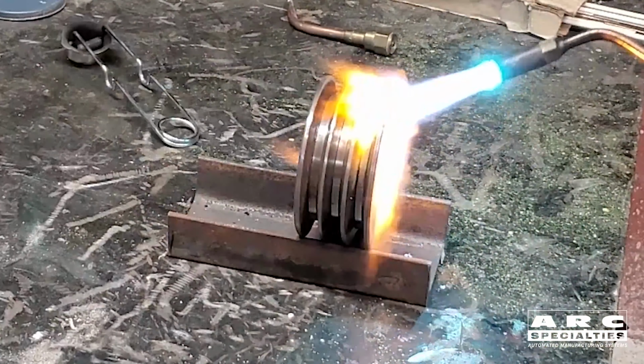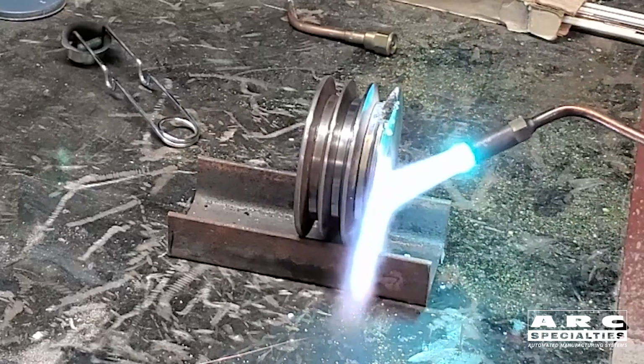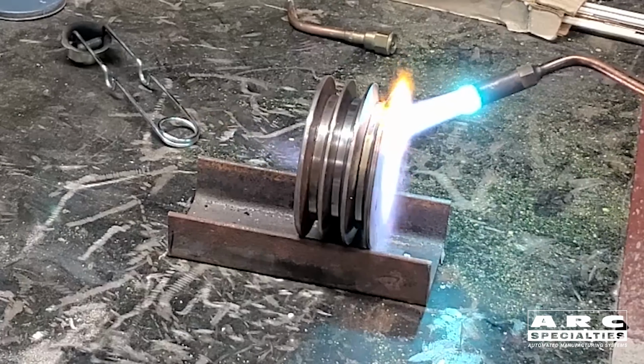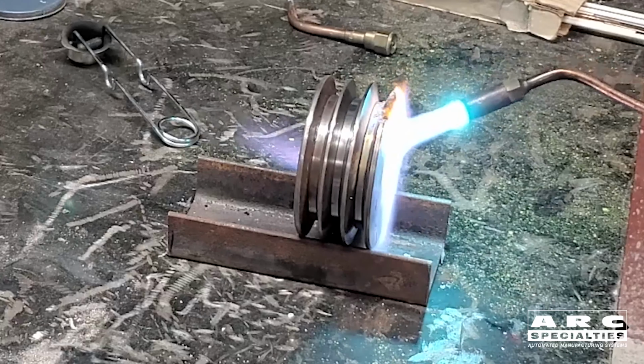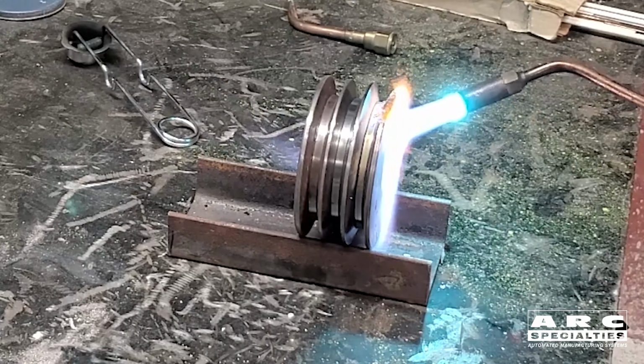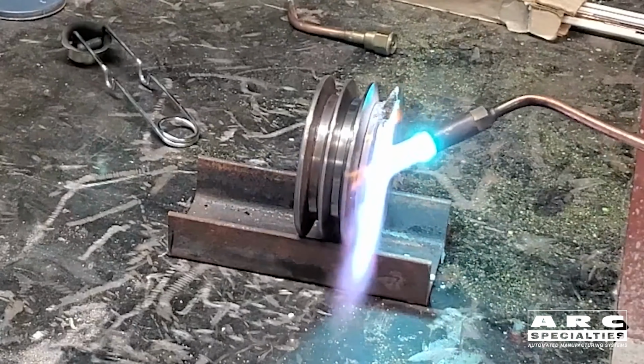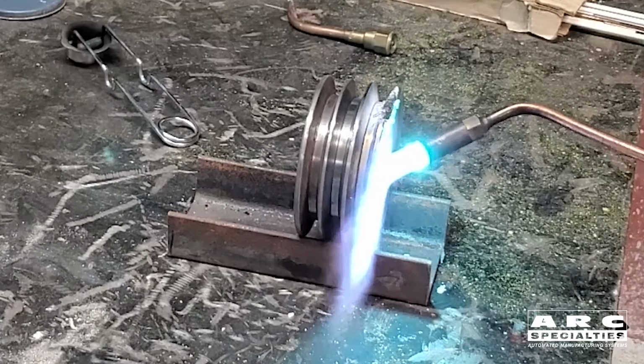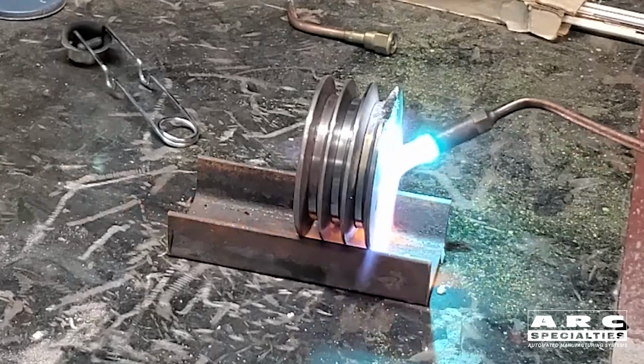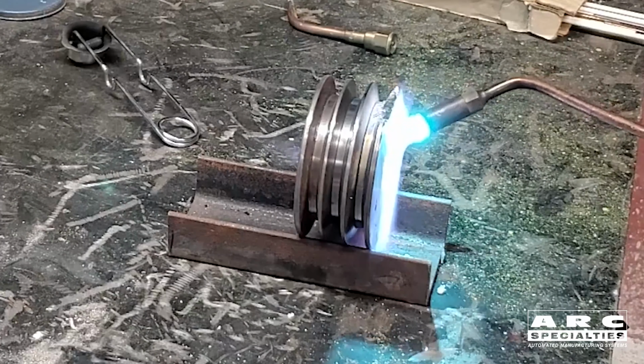Before we start brazing, it's best to preheat the part for a couple of reasons. First, it'll make the part easier to braze, and second, it will reduce the stress by having the entire part expand and contract together. So the way I control the temperature of the preheat is I just heat it till I see a dull red. That means I'm getting a localized area of 1,000 degrees Fahrenheit. Whole part's probably at 800 or so. It's not critical, we just want the part hot.